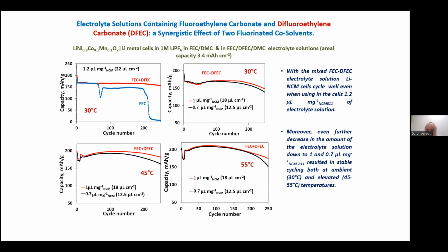So now, more examples, even at 55 and 45 degrees, using the combination of FEC and DFEC, we have very nice stabilization even at elevated temperature, and we can even use very small amounts of electrolyte solution per milligram of cathode material. These are nearly practical amounts, and even at 55 degrees C, we demonstrate stabilization, even if we have only one microliter per milligram of electrode material. So we see that by using more than one co-solvent, we can stabilize the system further.